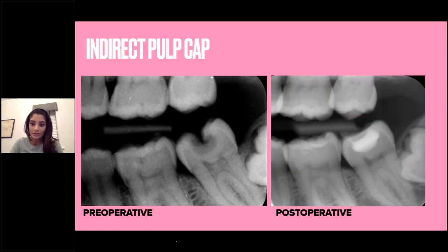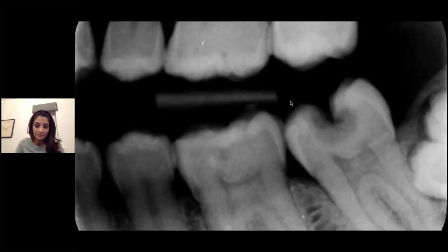This was the post-operative result. We can see here the bulk fill composite. There's a layer of normal composite on top of that, and you can't actually see the Biodentine pulp cap very well. That would be the one negative of Biodentine that I could think of, the fact that it isn't very radio-opaque. It's got a radio-opacity just over that of dentine, so sometimes you can't always see it very well on a radiograph. I've got a video of how I treated the case, so you can have a little look.